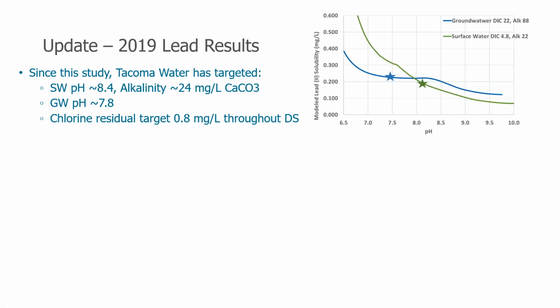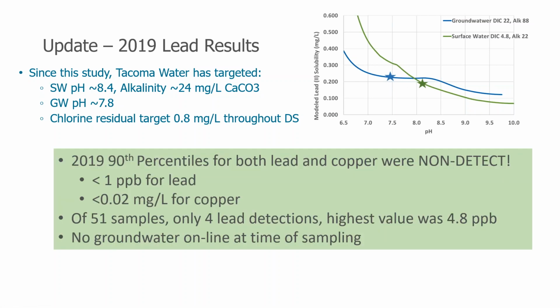So now just an update on where Tacoma is now. Since this study, Tacoma had targeted a pH of 8.4 for the surface water, so sliding the star down a bit to be even lower on the lead solubility curve. Groundwater pH of 7.8, just to ensure they're in the flattest part of the curve. And they've been targeting a chlorine residual of 0.8 through the distribution system, and their 2019 monitoring, the 90th percentiles were non-detect for both lead and copper, which is really amazing.